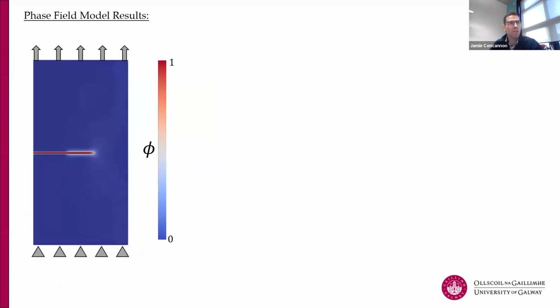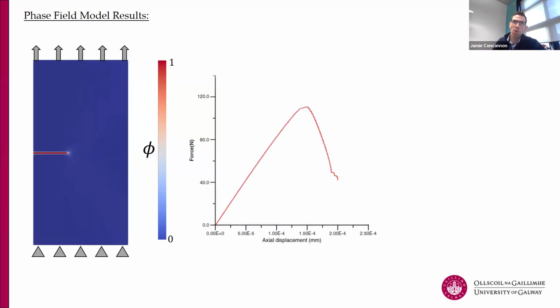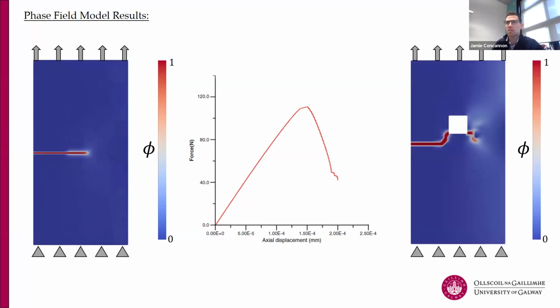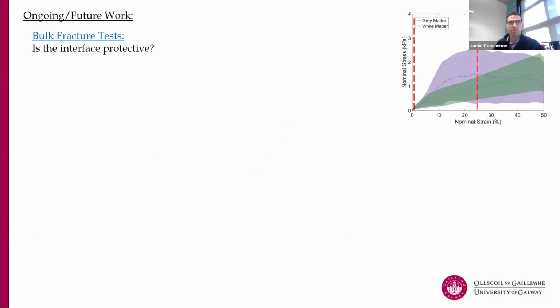So this is a very simple experiment where we just pull the top and hold the bottom, and you can see the cracks start to zip across. So these elements are initially blue, and then they turn to red as this phase parameter, or the crack, essentially grows. And you can see we grow up to our interface strength, and then we degrade down in terms of the exact same behavior that we see with our experiments, only that this is a small strain regime. And we can add in more complicated shapes, things like the lateral ventricles. This is obviously idealized for now, but this organic crack branching happens automatically because of the minimization.